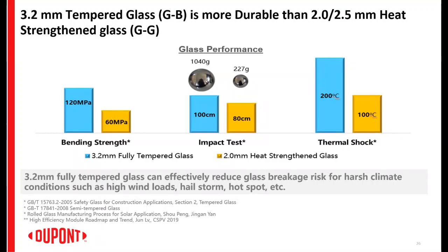If you talk about bending strength, that is going to simulate the impact of high wind loads. If you talk about the impact test, that's going to simulate the impact of hailstorms, and if we talk about thermal shock, that is going to simulate the impact of hotspots. As we can see, the results show that glass modules with weaker glass are more prone to bending and cracking during operation in the field.